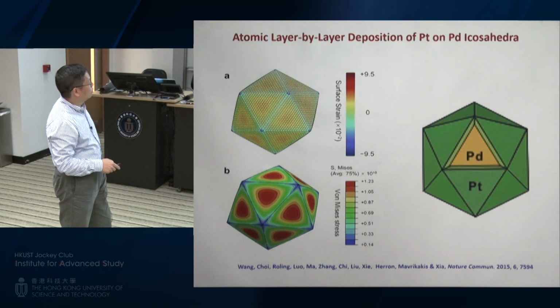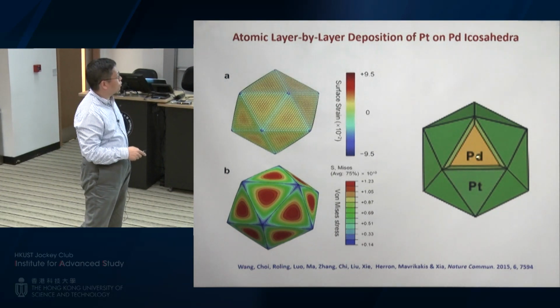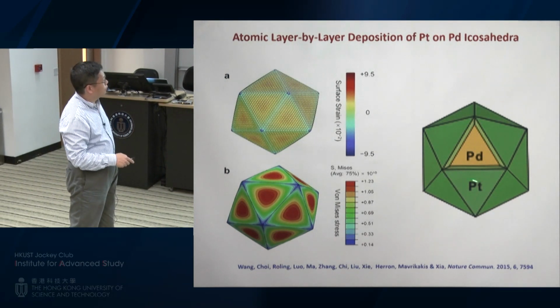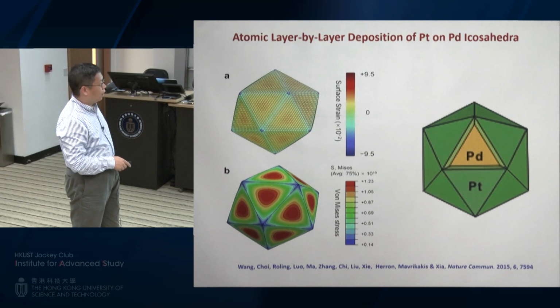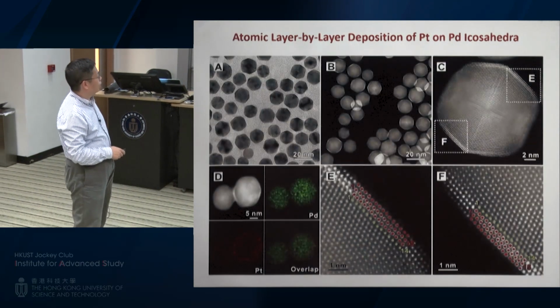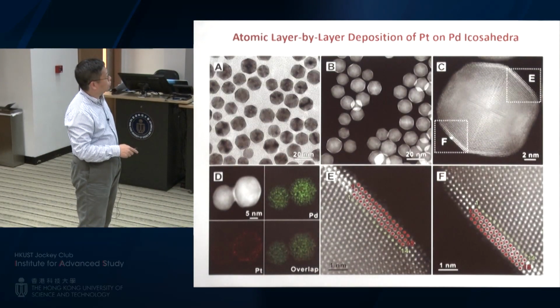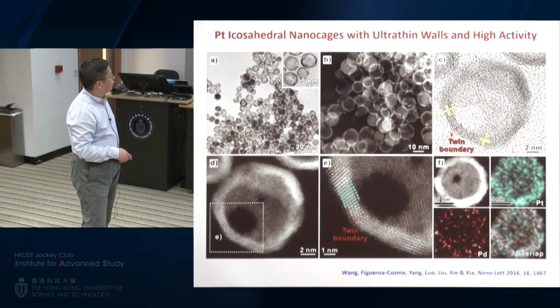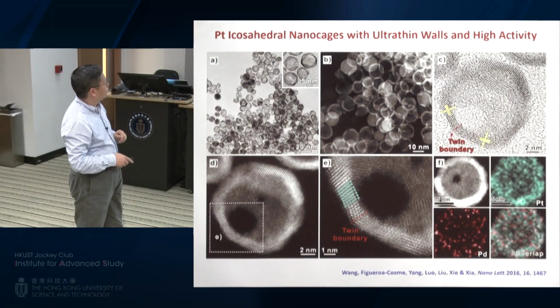the 1-1-1 facet. So we can take palladium icosahedra, coat their surface with platinum, and then etch away the palladium to form icosahedron-shaped platinum nanocages. So here I just show you the core-shell structure. You have a palladium core, and platinum being deposited on the surface. There are about 3 atomic layers. And eventually, you can etch away the palladium to form these hollow and porous icosahedral platinum nanocages. You can also maintain those twin boundaries on the surface.